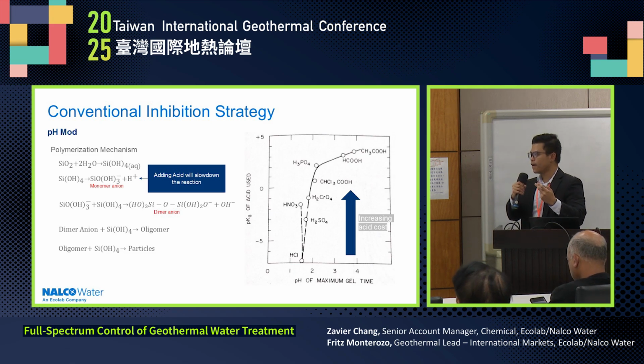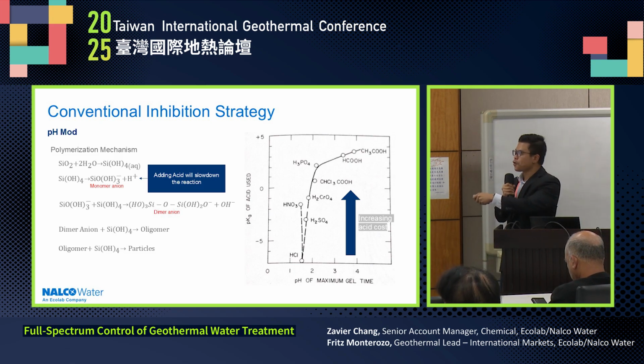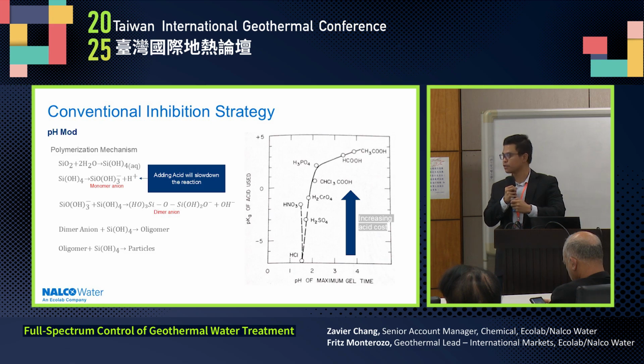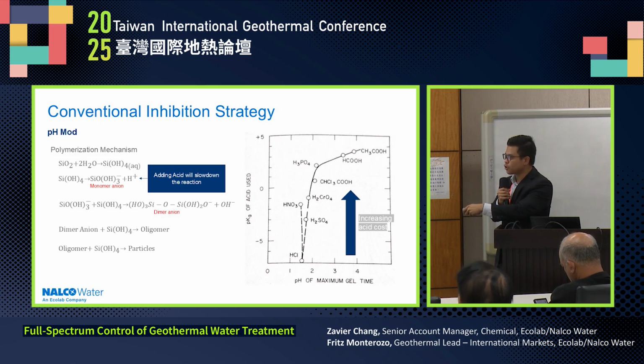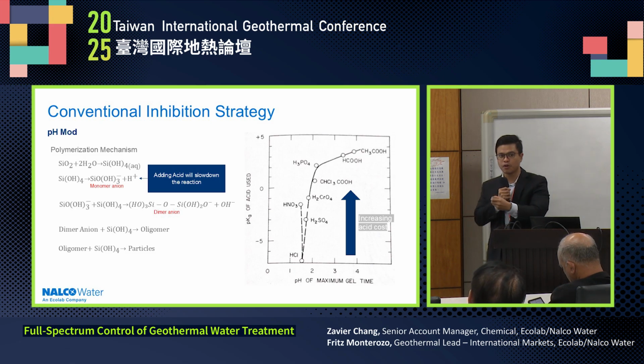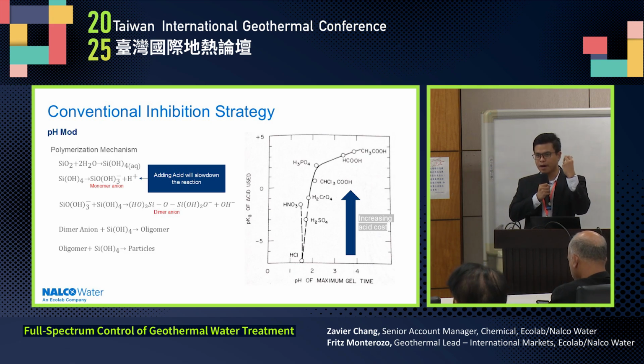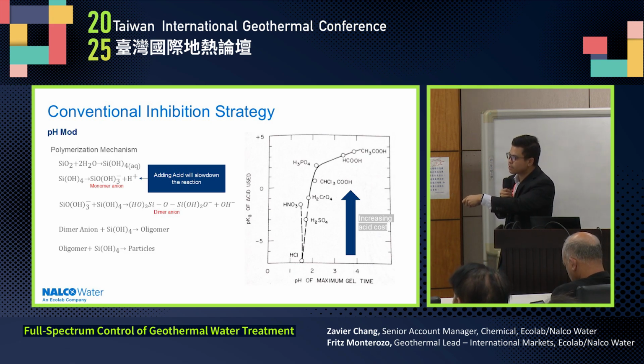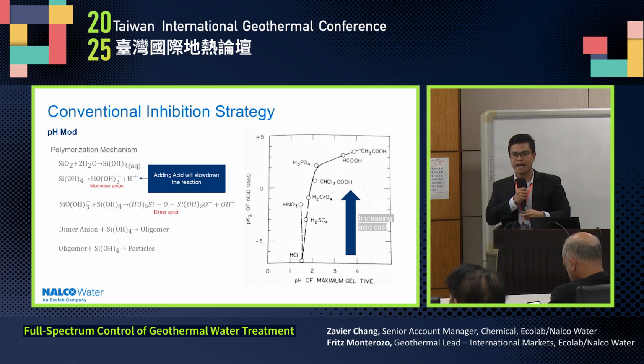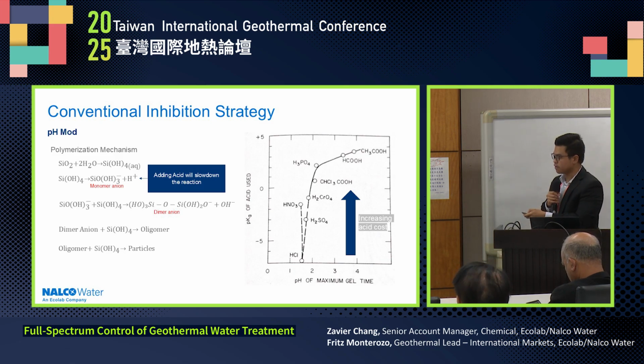So how do we manage silica scaling? A common method is called pH modification. You add acid into the solution to delay the polymerization. The polymerization of silica is catalyzed by hydroxide ions. If your system is near neutral to slightly alkaline, you have a lot of hydroxide ions. So your acid gives a proton into this solution and neutralizes your hydroxide ions. So it delays the polymerization.